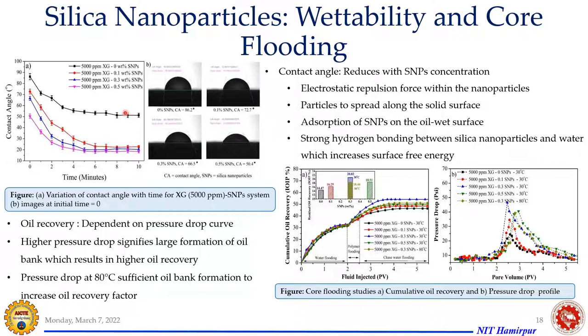Okay, so we have just put a drop of it and measured the contact angle with time. This is the pictorial diagram. You can see these are all reported at time zero. With no nanoparticles, you can see the contact angle reduces and reaches a stagnant value. So it indicates that the reservoir is more or less intermediate wet. Okay. So we know that our reservoir is intermediate wet. Now we are injecting nanoparticles and then we see how the wettability will be changed.